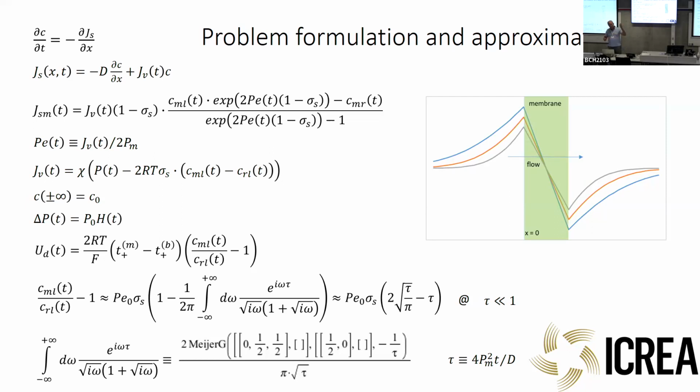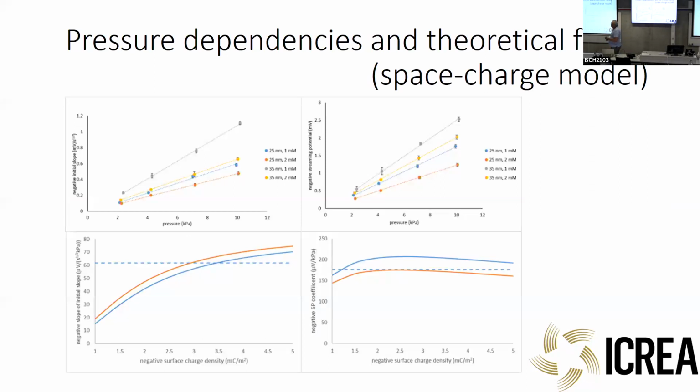If you go to even smaller pores, for example, it gets even worse. So I would say many people would call this streaming potential, but this is not streaming potential. This is mostly diffusion potential caused by ion rejection. And this is what we see in this time of salt measurements. Well, there are several checks.